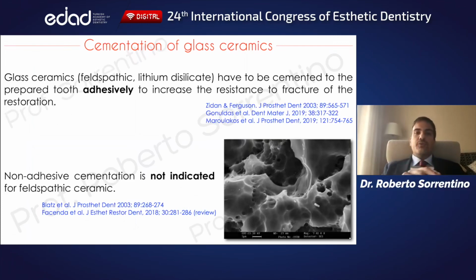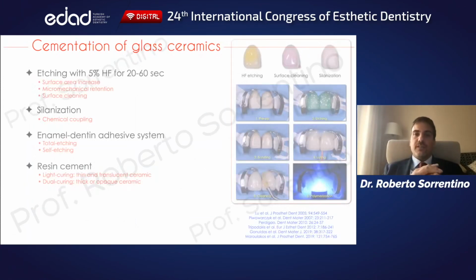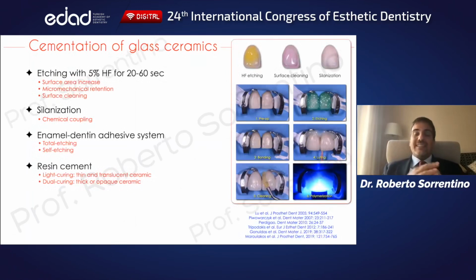Glass ceramics have to be etched with hydrofluoric acid for 20 to 60 seconds, according to the silica content, and silanized. Then you can go for total or self-etching adhesion and resin cements, light cured in case of thin and translucent ceramics, or dual cured in the presence of opaque cores or thicker restorations.